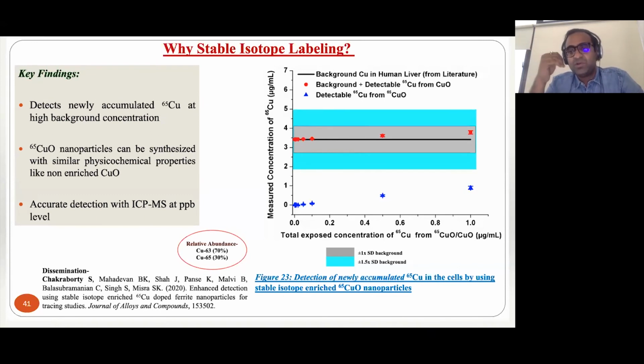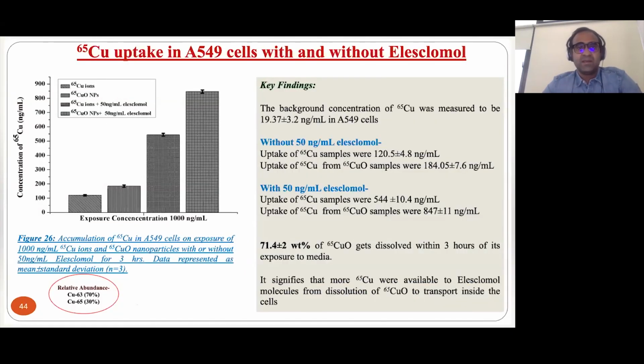So what we want to do is minimize the dosage, whether it is of the Elesclomol or of the copper oxide. But to minimize the dosage, you'll always have a problem of distinguishing it from the background concentration. So what we did is we tried to label these nanoparticles with a stable isotope of copper, copper 65. Because it's a stable isotope, it's not radiogenic in nature, so we can actually track it forever, to the extent that even if this copper 65 is going inside, the efflux of this, we can also measure that.